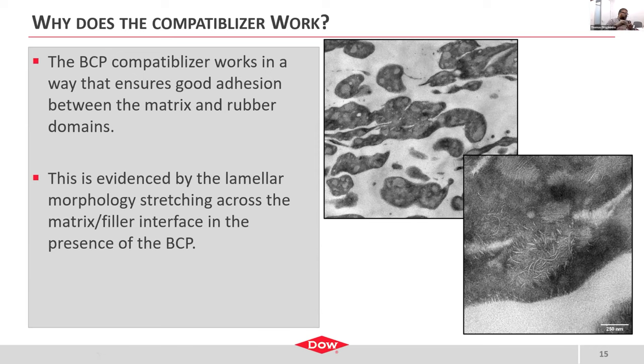These lamellae that overcross the interface really work to tie those two incompatible materials together, increasing the toughness and therefore the mechanical properties related to the resulting TPO material. So that's a way that we often work to lightweight our cars by swapping out metal materials for plastic materials while not sacrificing safety by keeping a highly tough material that we can keep on the